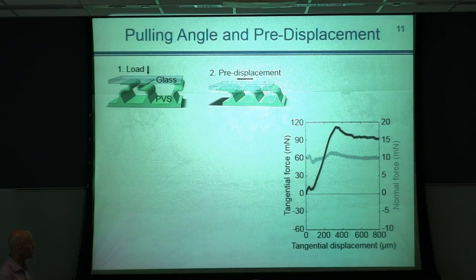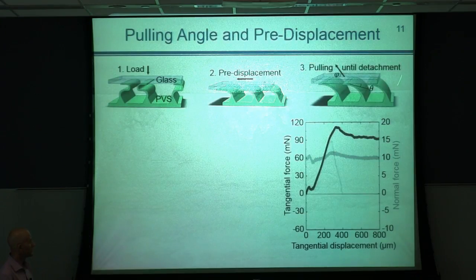Now, actually, we wanted to test pull-off force when the surfaces started to be withdrawn from each other at different points. And this is a schematic representation. So after a certain pre-displacement is applied, we start pulling our counterface at different angles and measure the forces that are generated at this moment. The black line represents tangential forces generated at the time of the pulling, and the gray line represents the normal component. So the lowest point actually gives us the pull-off force, the force needed to detach the surfaces from each other.